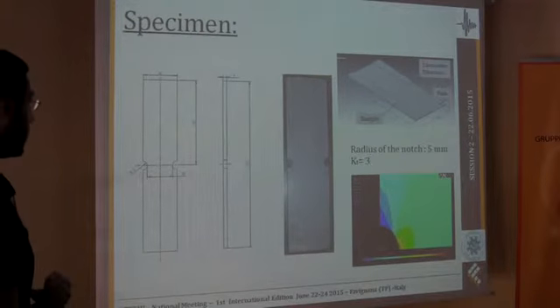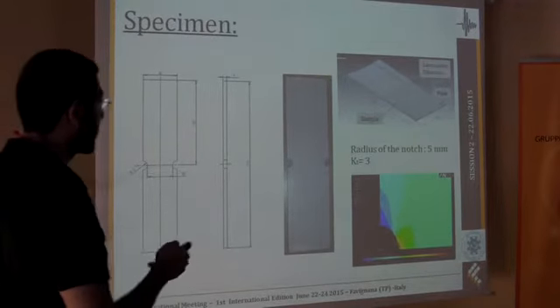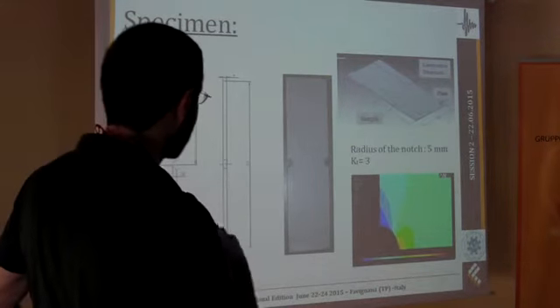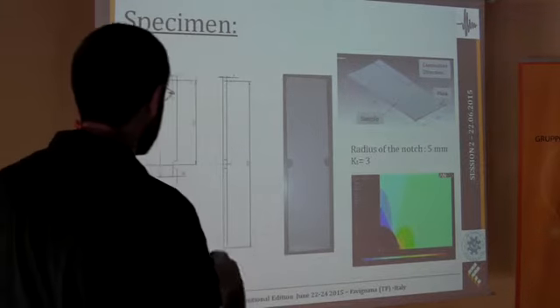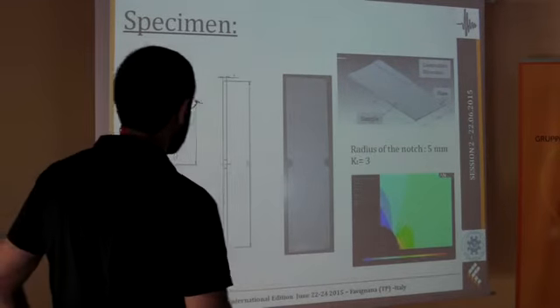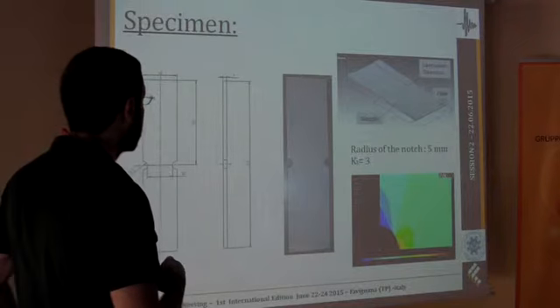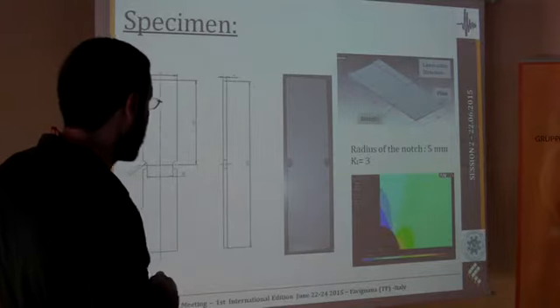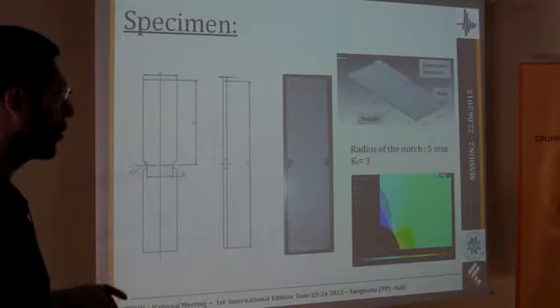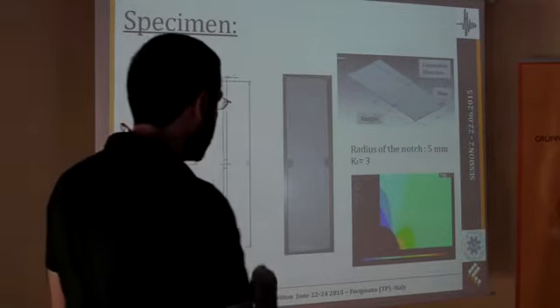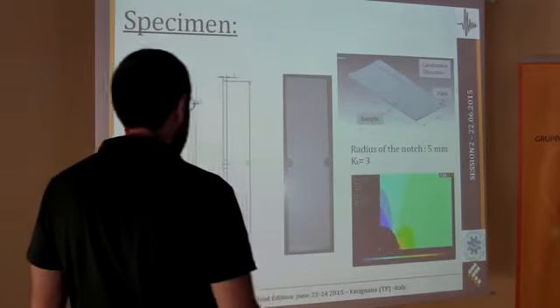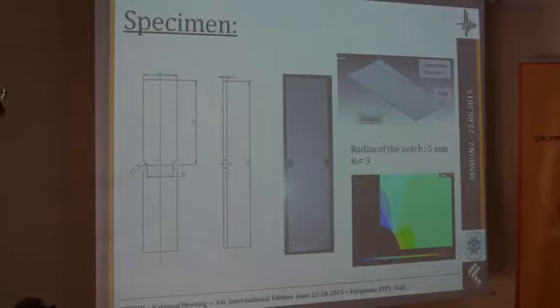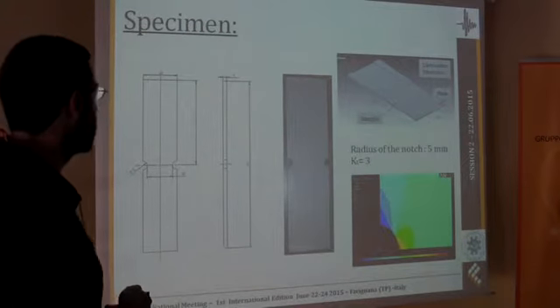This is the specimen, this was cut by a plate of titanium grade 5, they were laser-cut in order to not introduce residual stresses due to cutting, and also notches were cut by laser, in order to introduce an area where there is a well-known stress concentration. This is the stress concentration factor as was calculated by a simple finite element analysis model.